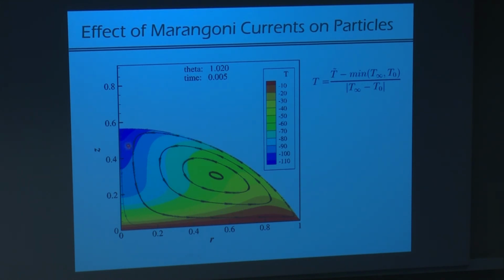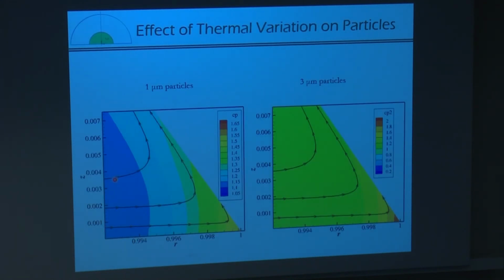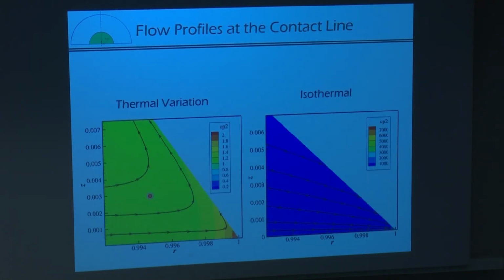So rather than having a liquid going to the contact line as the drop evaporates, you have this circulating flow within the droplet. And when we do that, the 3 micron particles don't accumulate as fast in the contact line area over here. And so this shows that the particles aren't depositing as quickly because of the Marangoni flow, which is consistent with what we see with the experiments.